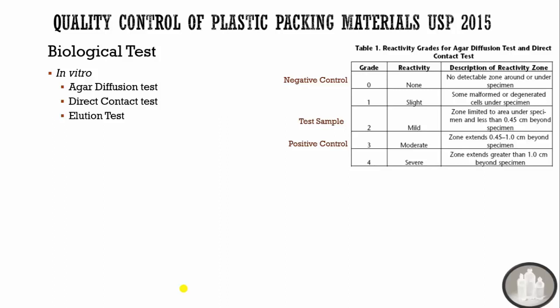In the in vitro test, cell culture is used and the influence of extract of plastic material on the cell culture is determined by different techniques. The negative control is high-density polyethylene reference standard material, which qualifies the test according to USP. The positive control is polyurethane film containing zinc diethyl dithiocarbamate or zinc dibutyl dithiocarbamate. The positive control may have a cytotoxic effect causing degeneration of cells, while the negative control does not have any cytotoxic effect.